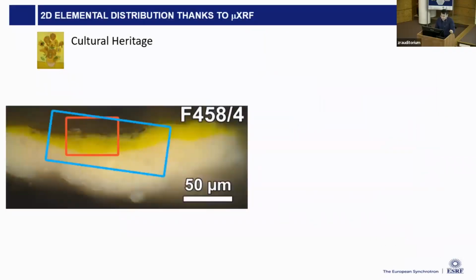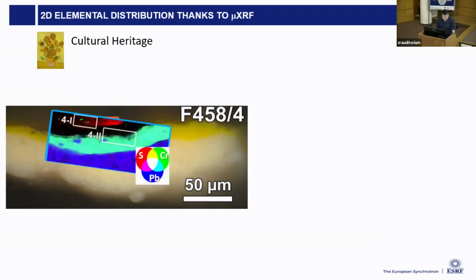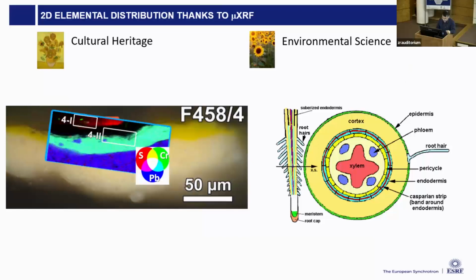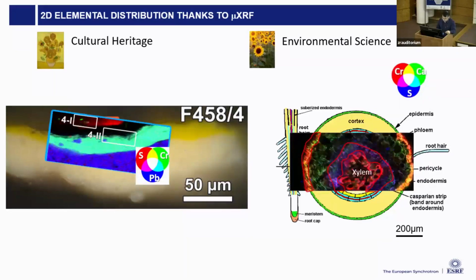At ID21, we usually start our experiments with acquisition of 2D XRF microfluorescence maps in order to reveal the elemental distribution of the elements of interest. In the painting, we see that chromium is concentrated in the yellow layer, while in the plants, we see that the chromium is not only in the epidermis, which is the outer layer of the plant tissue, but also it has penetrated all the way up to the xylem, which is the most internal part of the root.